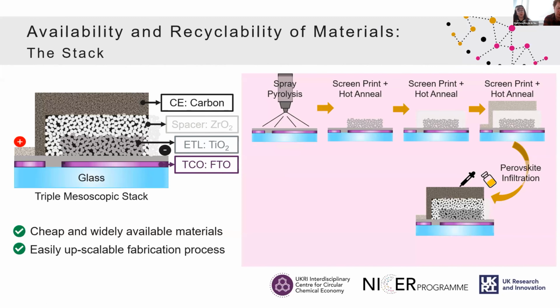Now, the fabrication process is very easy to upscale because it's a sequence of subsequent layer depositions. So you start with the spray pyrolysis of the compact layer of titania, and then you just build layers and anneal them progressively until you get the full stack. And they are not as low temperature as the perovskite itself, but I think the maximum temperature you will be working with is 500 degrees, which is significantly lower than the fabrication temperature for the standard commercial devices. And then in our last step, you just infiltrate the perovskite through, it crystallizes by heating at around 100 degrees. So that makes the process very easy and upscalable to make.